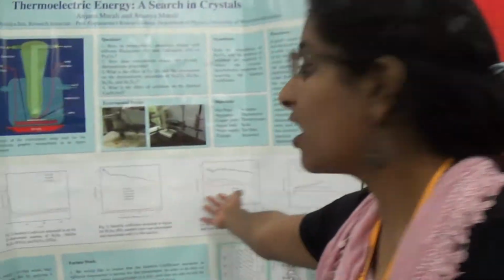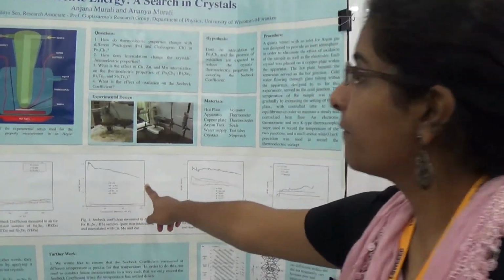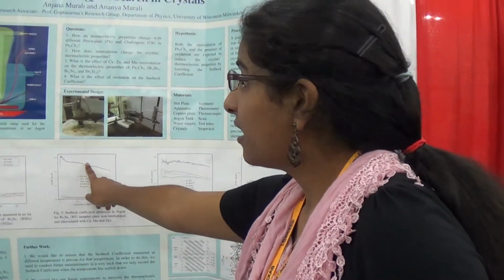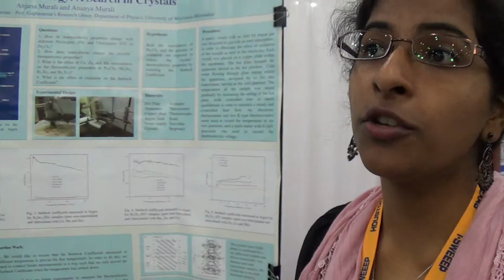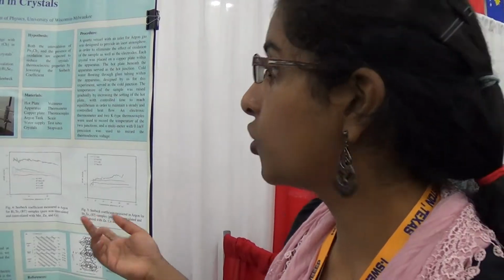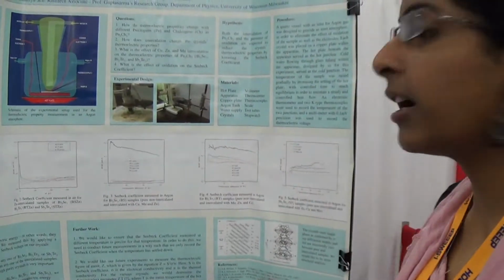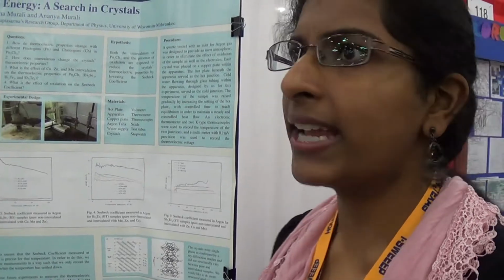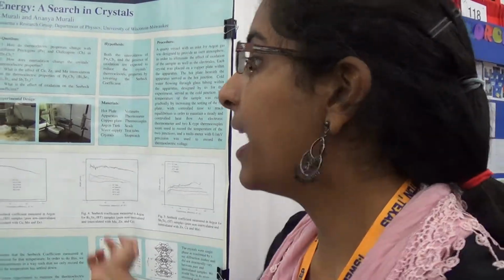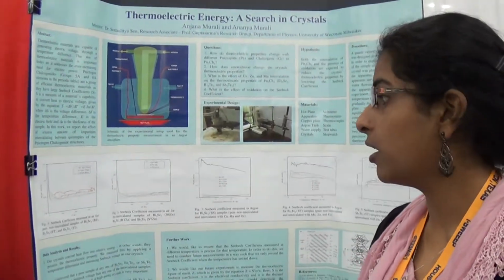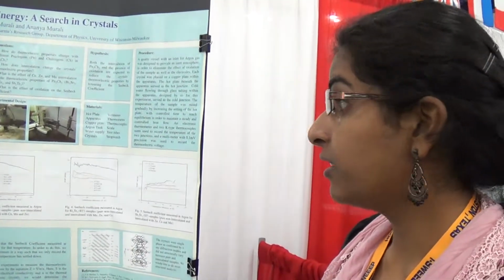So we attached an argon tank to the apparatus that we designed to eliminate any effects of oxidation, and the results are clear. These three graphs are from this year's experimentation in an inert atmosphere, and as you can see, without oxidation, in the inert atmosphere, you produce much higher Seebeck coefficients, which means that we're producing much more voltage. So in the argon systems, we saw Seebeck coefficients of around 0.3 compared to the ones done in regular room temperature, which produce about 0.04, which is a huge difference.